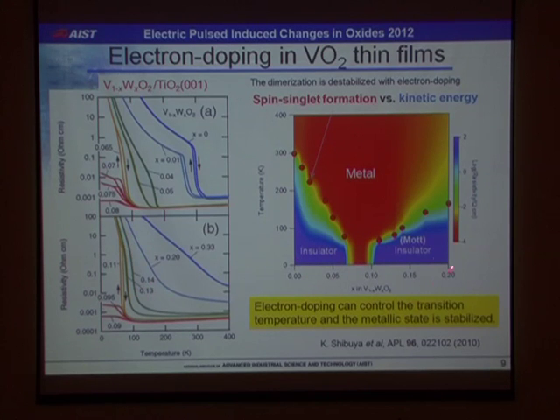Here shows a phase diagram of electron doped VO2. In the lower doping region, spin singlet formation is destabilized with electron doping. This is due to the enhancement of electron kinetic energy. And in the higher doping region, strong electron correlation of the vanadium 3+ band is likely to contribute to the formation of this new insulating state. Presumably this is a Mott insulator with an antiferromagnetic ground state.